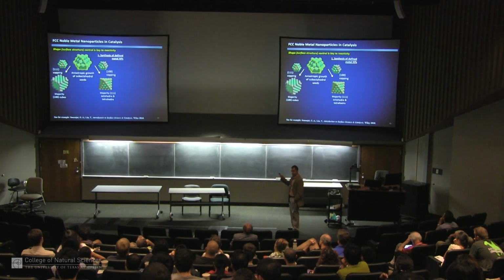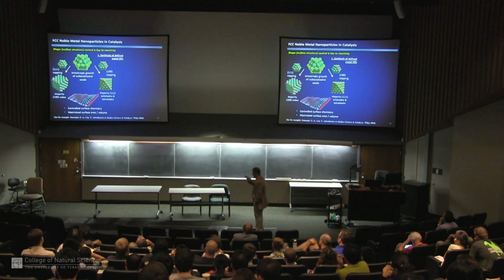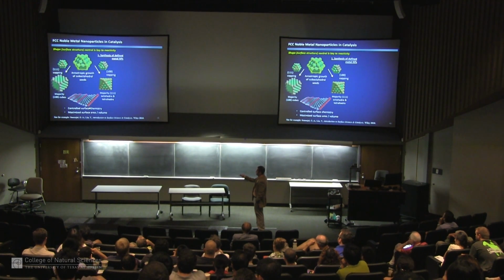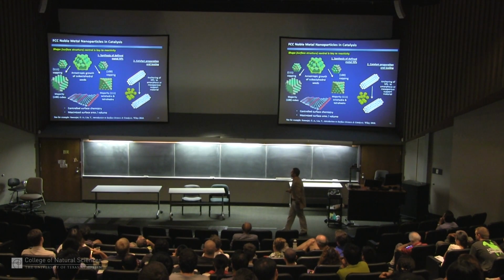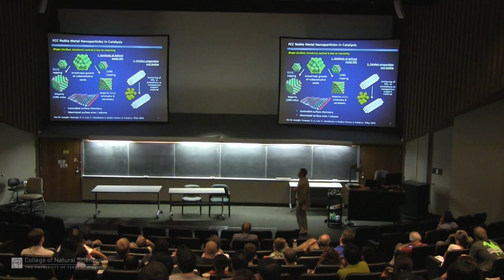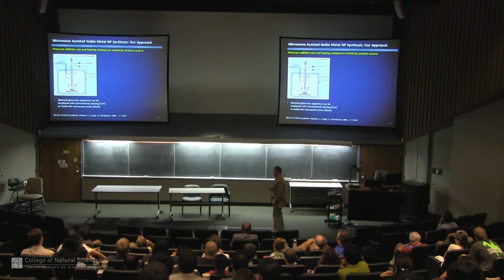This is a challenge, though, because you've got to do this in solution by adding atoms one by one. And really what we're trying to do is, instead of having to go the top-down approach, which is taking a crystal and mechanically grinding it to a certain shape, which means there's a lot of wasted metal, we're trying to do this from the bottom up in one step. And then we deposit them onto or inside a material that makes our composite catalyst, and then we can study them.